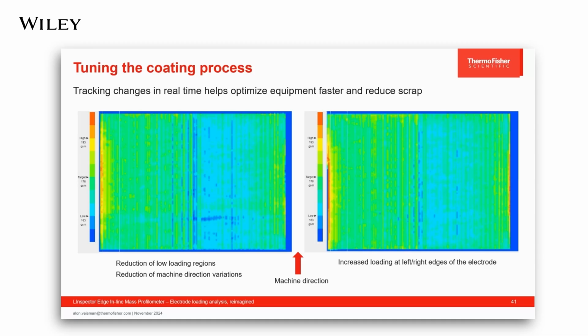In the example here, the operator makes a change to the process to correct for low loading regions. But in doing so, they create a problem on the edges of the electrode, where the loading becomes too high.